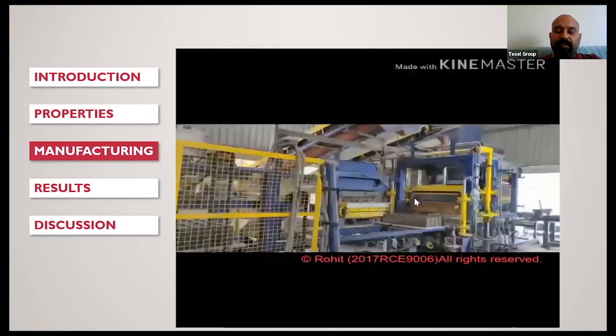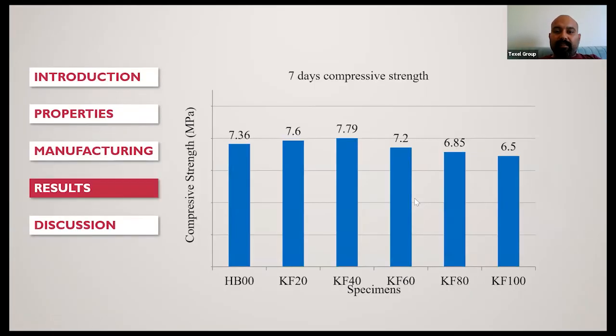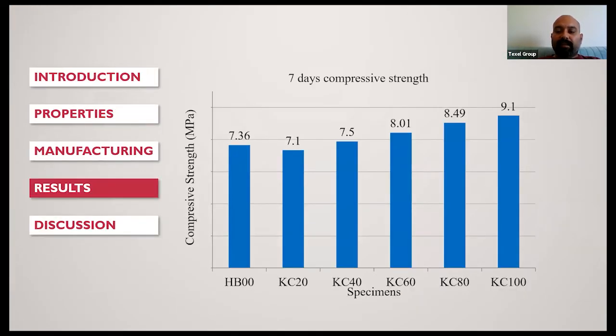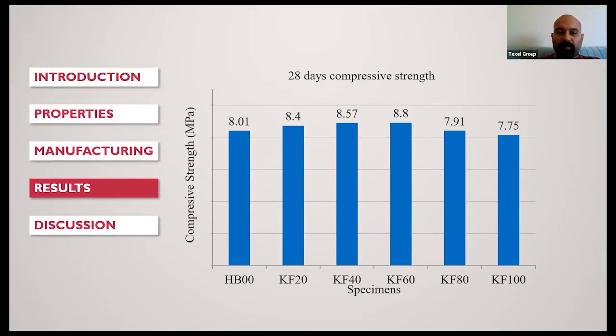I found that at 7 days compressive strength, replacement of fine aggregate up to 60% is somehow comparable to the control mix. In case of coarse aggregate replacement, 100% replacement shows better results compared to the control hollow concrete blocks. At 28 days compressive strength, it shows the same trend, with up to 60% replacement showing good compressive strength.